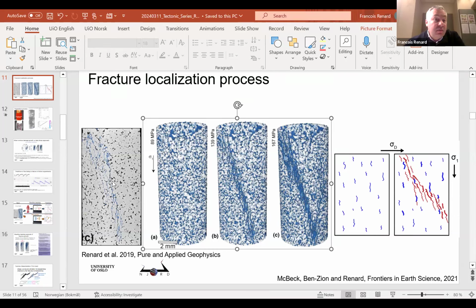Otherwise, it's challenging because how do you define a Gini coefficient? If you just look at the porosity, there is porosity everywhere. And even during the fracture, it will not change much. So for the Gini coefficient in this kind of rock, we have to find a clever way to look at it, because it is strongly influenced by the original distribution of the porosity. Thank you very much.